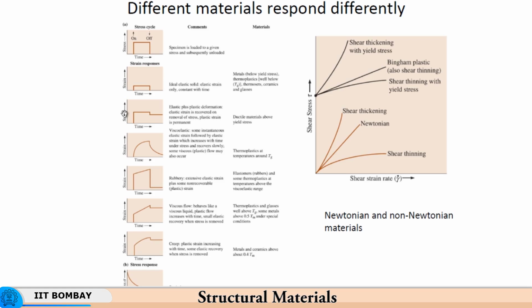Now, if you take a high temperature material, if you go to high temperatures, then the materials often become viscous. I had told you that the grain boundaries become viscous and they start responding to strain rate. So, the strain versus time will have a slope continuously varying with time, because these materials respond to the strain rate, meaning that as the strain increases, the strain rate changes, and therefore the material will respond in terms of changing strain. As you see, the stress is constant, the stimulus is constant, but the strain response is changing, because initially the strain increases very rapidly in response to the stress, but then because of viscous effects the strain rate drops.